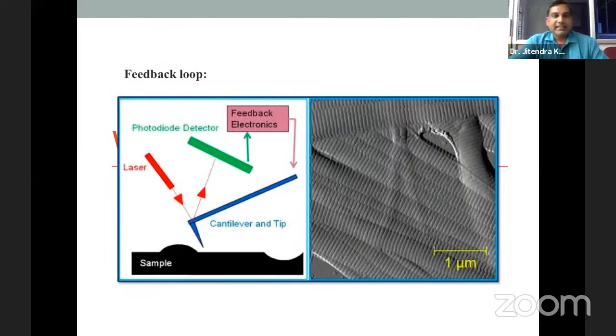This is the basic feedback signal, when the tip moves over the surface in a raster scan. According to that, your cantilever tip moves over the surface. There are three modes we use in atomic force microscopy. If your sample surface is very smooth, then you go for contact mode. If your surface roughness is a little higher, around 1 or 2 micron, then don't go for contact mode, otherwise your tip will break.